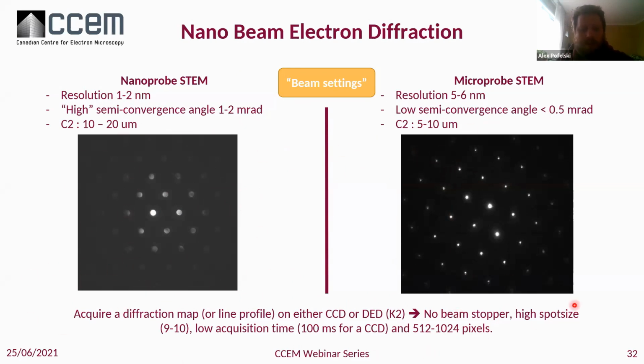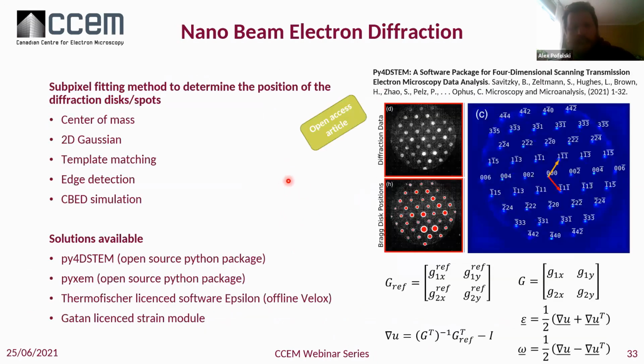So this is what you might be more commonly referring to as the STEM method. You acquire a map of diffraction patterns, and then you will have to process them to find the strain. Important here is that you have two types of diffraction that might be targeting two different processing methods, because they are not exactly the same here. And the same thing as before, if you just limit yourself to finding the maximum position of the peak, your sensitivity will be too poor.